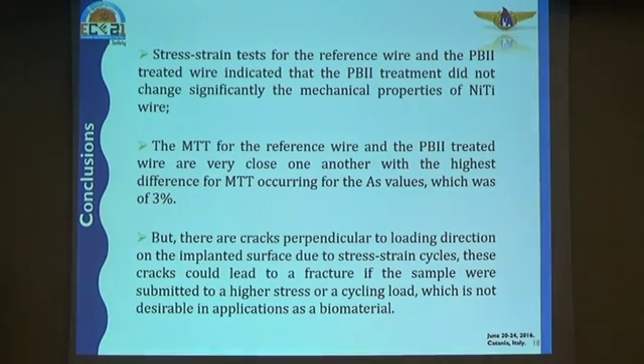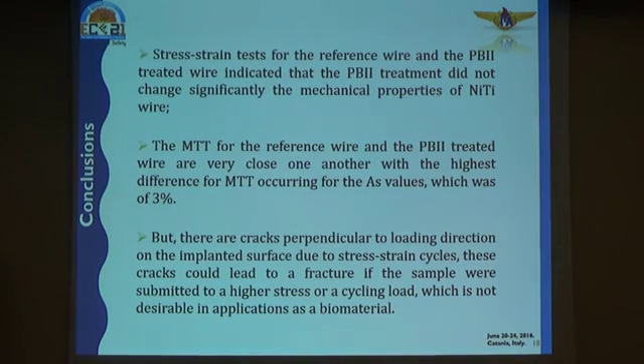And here are some conclusions. Stress strain tests for the reference wire and the PBII treated wire indicated that the treatment did not change significantly the mechanical properties of the nickel titanium wire. The transformation temperatures for the reference wire and the treated wire are very close to one another, with the highest difference occurring for the As value, which is the start of austenite temperature, which was about 3%.